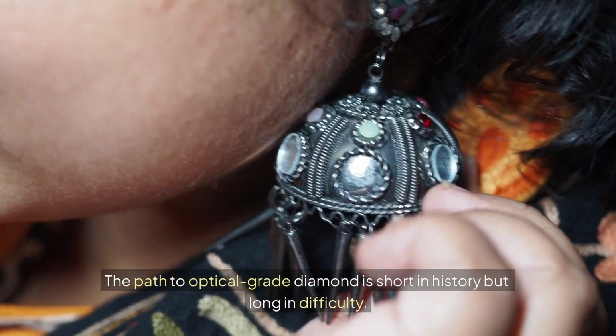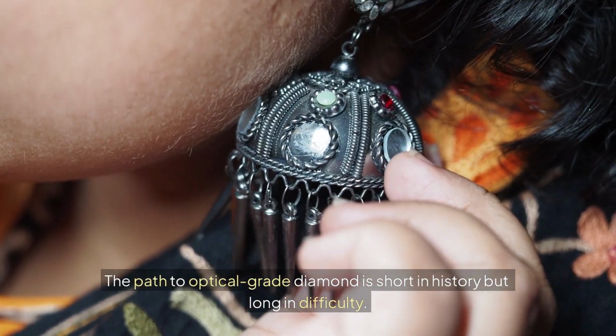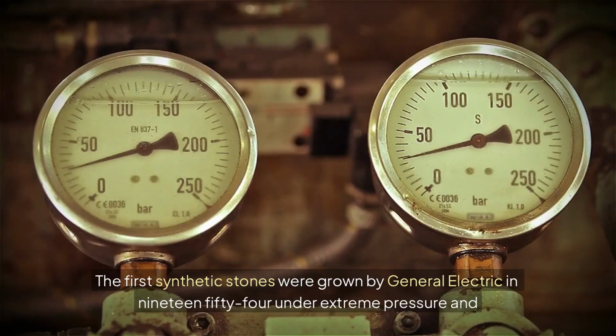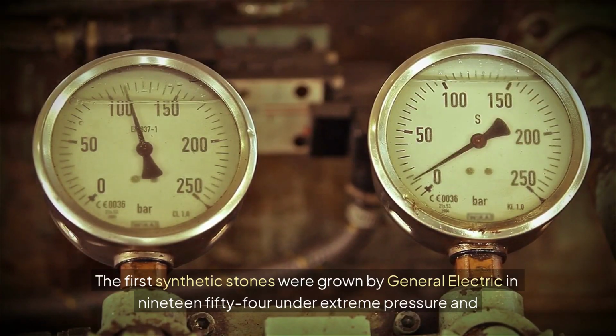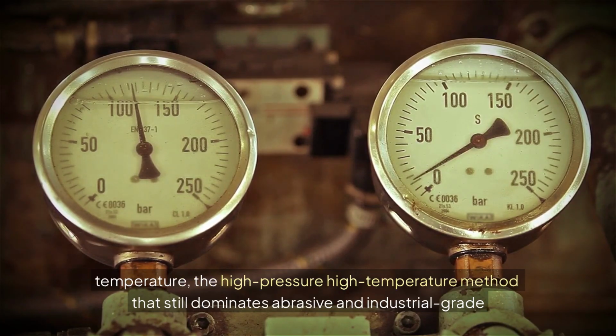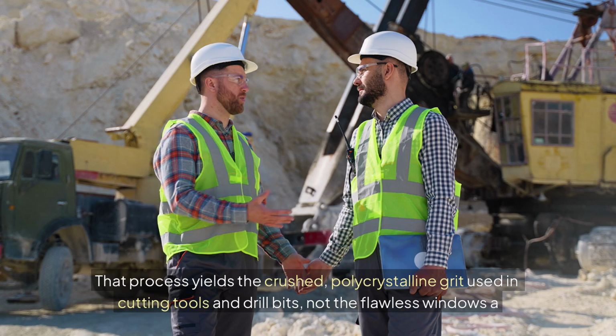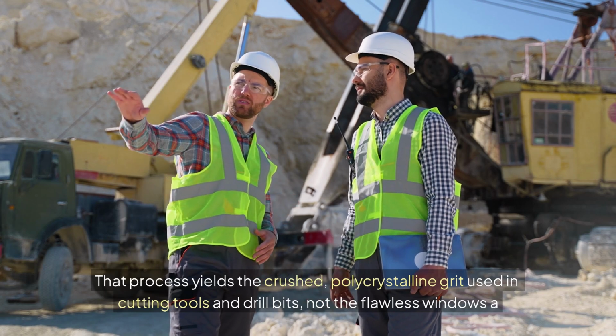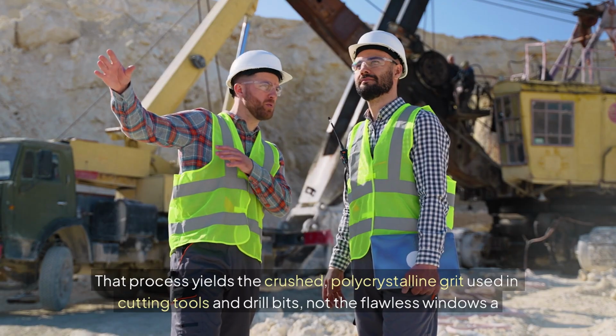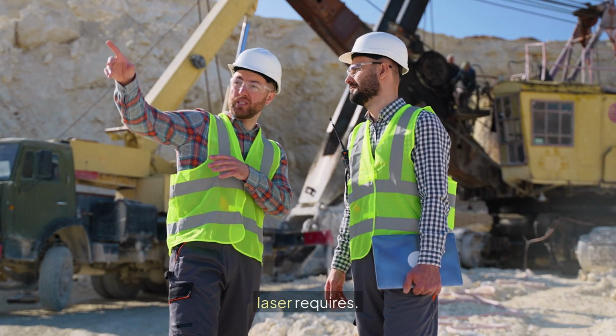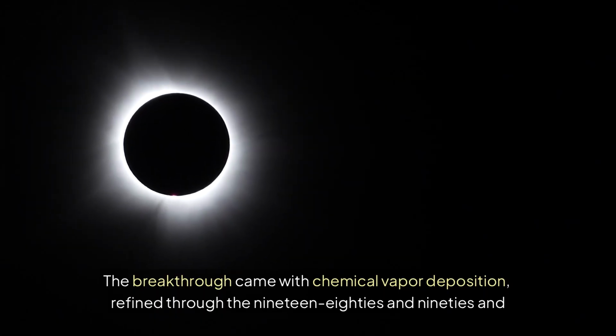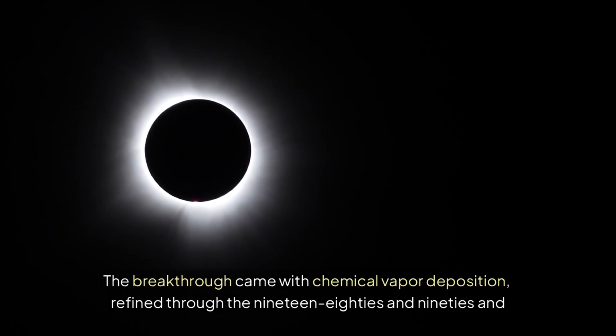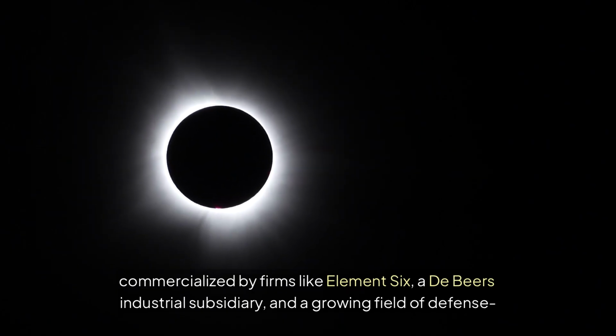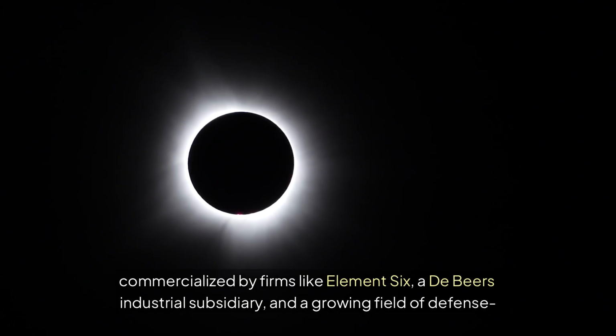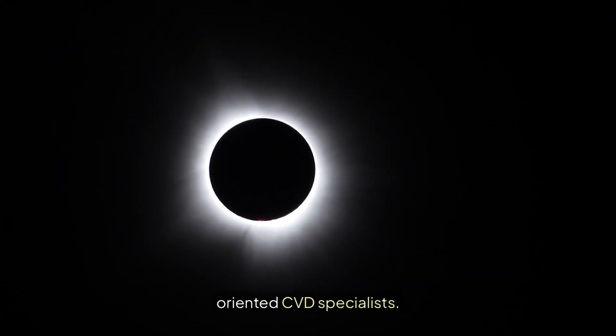The path to optical-grade diamond is short in history, but long in difficulty. The first synthetic stones were grown by General Electric in 1954 under extreme pressure and temperature, the high-pressure, high-temperature method that still dominates abrasive and industrial-grade production. That process yields the crushed, polycrystalline grit used in cutting tools and drill bits, not the flawless windows a laser requires. The breakthrough came with chemical vapor deposition, refined through the 1980s and 90s, and commercialized by firms like Element 6, a De Beers industrial subsidiary, and a growing field of defense-oriented CVD specialists.